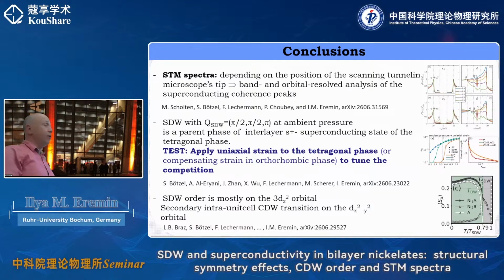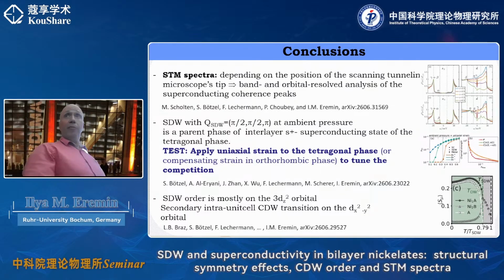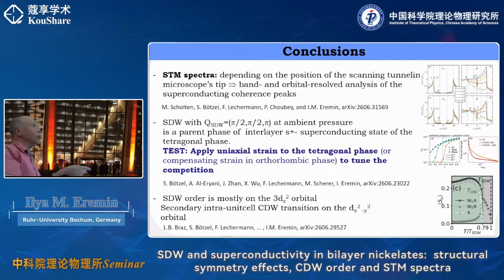Okay, so those are the three messages that I have. STM is a very interesting experiment, but you need to take some care, and moreover, it can produce some filtering effect, which might be interesting to discuss, not only in nickelate, but in any other material. For example, for trilayer nickelate, that is also known to feature a spin density wave. If we believe we deal with an S plus-minus superconductor, this magnetic order with pi over 2, pi over 2 is really a parent phase. So it really is the one which gives rise also to superconductivity.